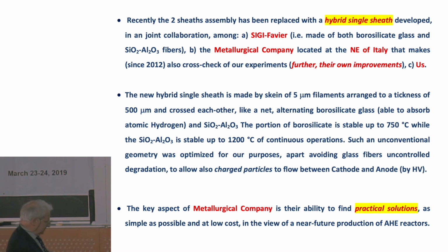The problem of this fiber took quite a long time to solve, because the glass sheet is destroyed at about 700 degrees, but we realized going to high temperature is better. At first we made a double sheet with the internal glass sheet and the second quartz alumina, but it was too thick. So we were able to